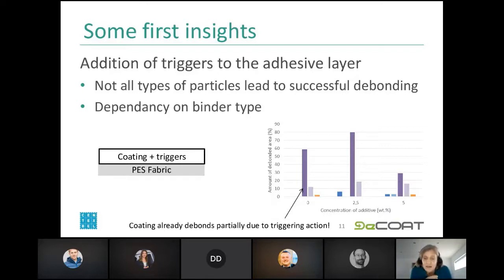If we add triggers, we can improve this debonding. But when we add different concentrations, we already see a different effect on the debonding. So we really have to fine tune the amount we put inside the coating, and take good care of which coating we are putting it in. So there's quite some investigation still going on to find the correct parameters.